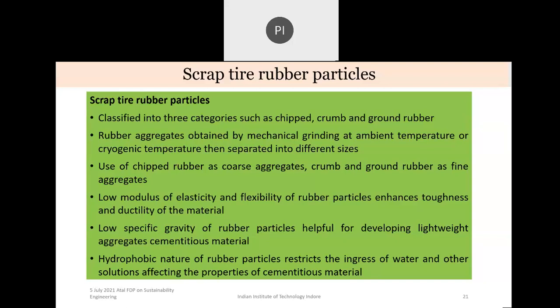Now, rubber aggregates are obtained by mechanical grinding at ambient temperature or cryogenic temperature, and then they are separated into different sizes. Now, we can use chipped rubber as coarse aggregate and crumb and ground rubber as fine aggregate. So it has multiple uses depending on the size in which we extract the rubber particles. It has a low modulus of elasticity and ductility of the material. So that is the USP of this material, that it has a low modulus of elasticity, and this flexibility is giving us higher toughness and ductility. And also it has low specific gravity. So this helps basically in developing lightweight aggregate cementitious material. The hydrophobic nature of rubber particles restricts the ingress of water and other solutions, which affect the properties of cementitious material.